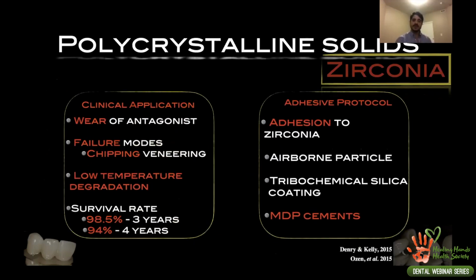Another interesting aspect of zirconia is that there is a misunderstanding of what hardness and strength mean. Some people think that because zirconia is hard and has a high strength, it will cause wear on the antagonist. And that's not what the literature shows. The literature shows that the wear of the antagonist with zirconia that is glazed and polished is just as good or better than with the other ceramic materials.